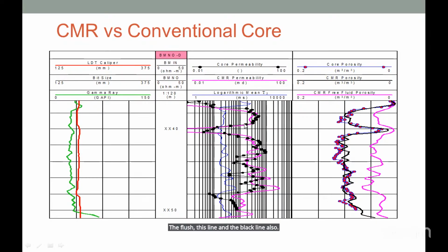Also, you can calibrate the permeability, as we see here. The black dots are the permeability points coming from the core, and this line represents the CMR permeability. Actually, it has a very good match with this data. This is the best tool for calibration of the NMR or CMR using the core data.